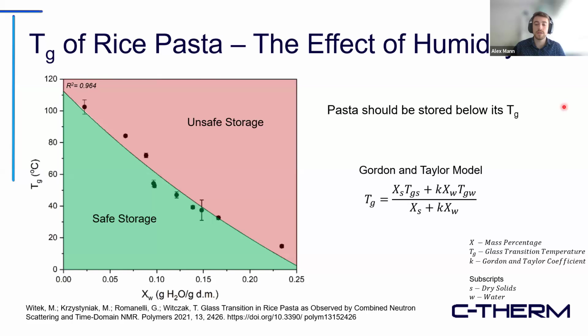So the takeaway is that as we increase the humidity, the glass transition temperature decreases. So what that means is that as we get more humid, the temperature at which we can safely store this pasta decreases. So if we see here at around 20 degrees Celsius, which is about ambient, follow across, and the mass fraction of water in the pasta cannot be above 0.18, or it can't be more than 18% water by mass. So that's great for storage condition if you have it on the shelf at home, or if you're transporting it from the factory to the market.